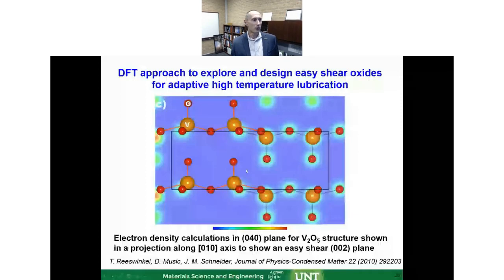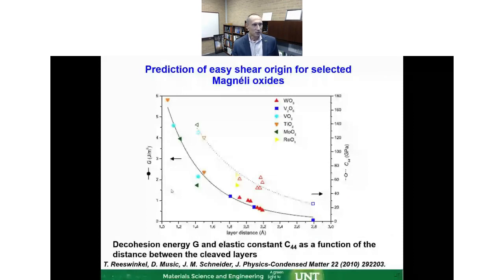So what we can do, this is work from my good collaborator and friend in Aachen, Jochen Schneider, who was working with T. Reeswinkel and Denis Music. In 2010 we did calculations of some of these double oxides, trying to locate the low shear modulus directions in these oxides, which will lead to lubrication. We looked at the electron density populations, trying to identify where the electron density is lower, along which planes, which can then lead to calculations of the cohesive energy, leading to shear modulus estimations, and understanding which one can provide lubrication. So the results are shown here.